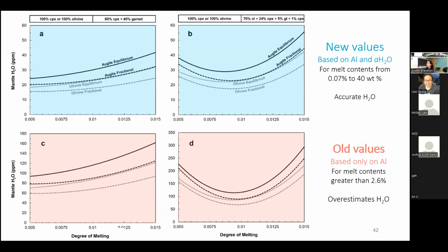And that's going to look like this, where you have to run some more models. And in fact, I've accounted for a variety of different scenarios here to try to get a realistic constraint on what the interior water content looks like. So I run equilibrium models and then fractional crystallization models of those different magma chambers. And that's characterized by the degree of melting in those chambers. So you can see that we simply progressively crystallize the sample and see how water is partitioned into the mantle or into those pyroxenes. And then also we need to consider different mineral assemblages.